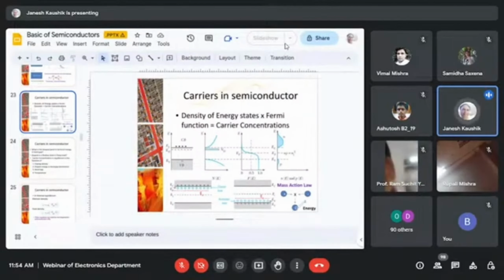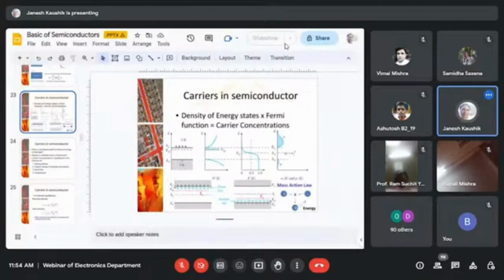But this zero is different for different materials, because it depends on the band gap. So when we calculate ni from the band gap, it is in the order of 10 to the power 10 for silicon, 10 to the power 6 for gallium arsenide, and 10 to the power 13 for germanium. But when you calculate for large band gap material like gallium nitride, it is 10 to the power minus 10. So you will say 10 to the power minus 10 is nothing, is zero. But if you ask me what is zero, I will say in engineering or in science, nothing is zero, nothing is infinite. A number can be zero for some application, but can be significant for another. Similarly, 10 to the power minus 10 is zero, and 10 to the power minus 20 is zero for even higher bandgap material. So it depends on the application, or which material you are using.